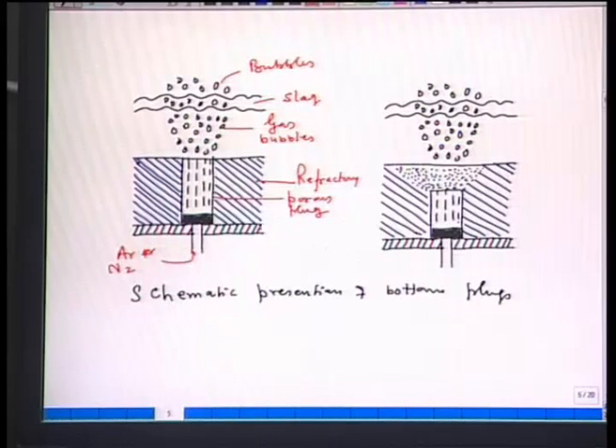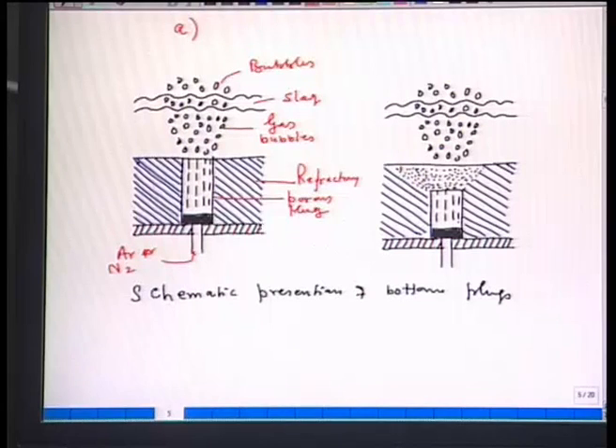So, here the stirring plug is a sort of very straight pipes. I mean this stirring plug has to be designed and has to be made. In this particular case, which I will put as A, that stirring plug is directly in contact with the melt. So, this is the melt. Stirring plug is directly in contact with the melt. What does it mean? You have to blow continuously and constantly a certain amount of gas, so that the bottom plug does not plug. If they plug, no gas will flow and the advantage of bottom stirring will not be there. In another design,